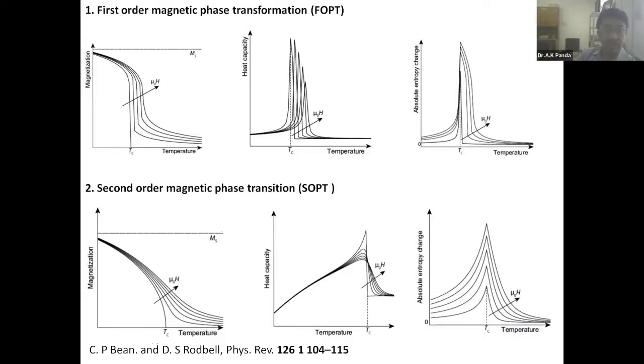Second order magnetic phase transformation is more like a continuum, in the sense that you do not have any structural transformations. So the drop in the magnetization, in the bottom left plot, you see that it's not very drastic. And so forth with the heat capacity and the absolute entropy change, right?